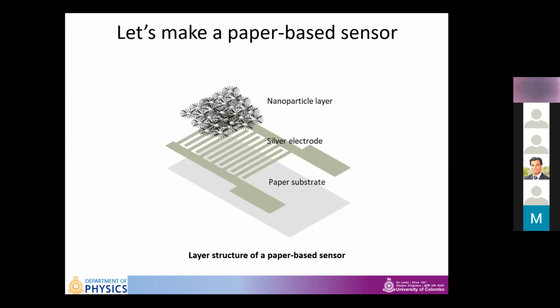Once the material is exposed to the chemical that we intend to sense, the resistance or the capacitance of the sensor measured across the arms of the electrode would change. We can calibrate the sensor by exposing it to known amounts of sensing chemicals and record the response. Then we can use that known response to find an unknown amount of chemical present just by looking at the capacitance or the resistance. These type of sensors are widely used in many gas sensing and other biological sensing applications.